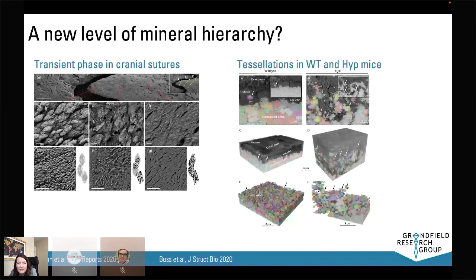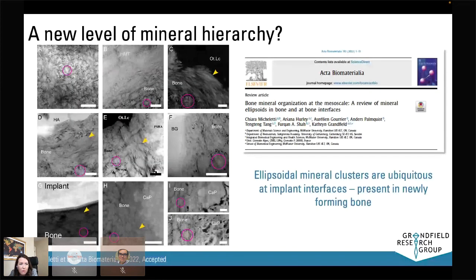Some of our work afterwards - this was a great project to do in the pandemic. We wanted to probe all of our previous work to see if these structures were there all along and we just didn't notice them. And in fact, they were. This is a review paper from one of my PhD students, and she took a look at a number of different biomaterials, such as bioglass, titanium implants, hydroxyapatite implants, and different calcium phosphates. What she found in all of these samples was that again, these ellipsoidal mineral clusters were ubiquitous, and they were present at bone implant interfaces as well. So they're also present in newly forming bone tissue.